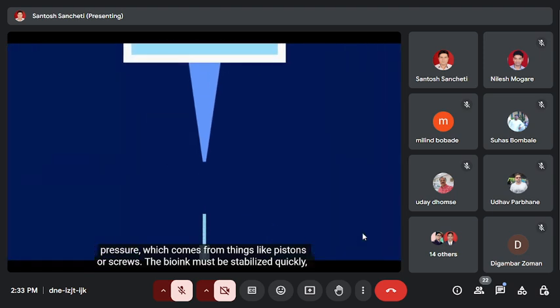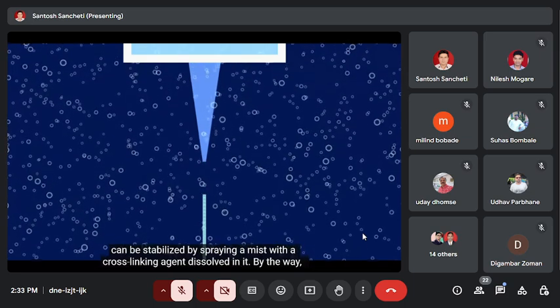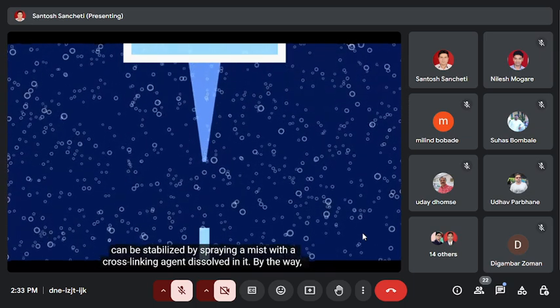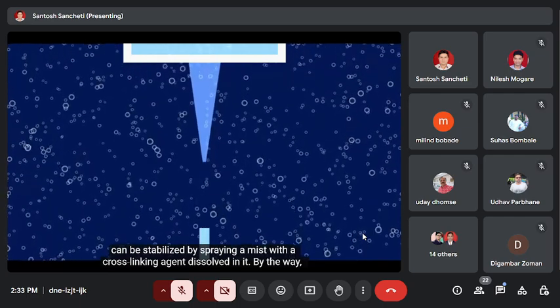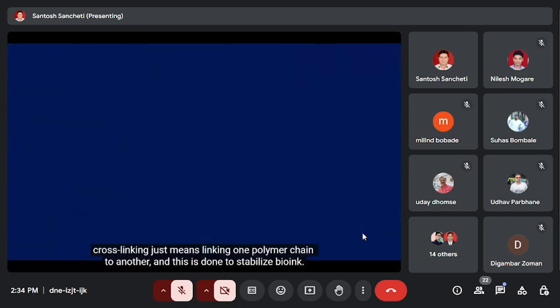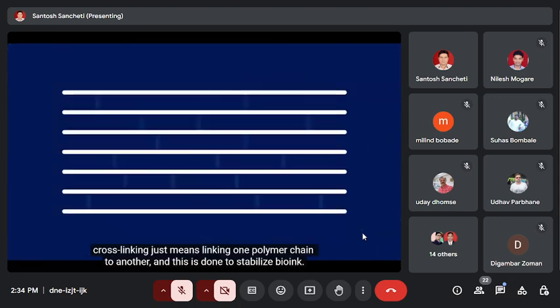The bioink must be stabilized quickly, or else it will not retain its shape. The bioink can be stabilized in a number of ways, largely depending on the hydrogel that is being used. As an example, during printing, the bioink can be stabilized by spraying a mist with a cross-linking agent dissolved in it. By the way, cross-linking just means linking one polymer chain to another, and this is done to stabilize bioink.